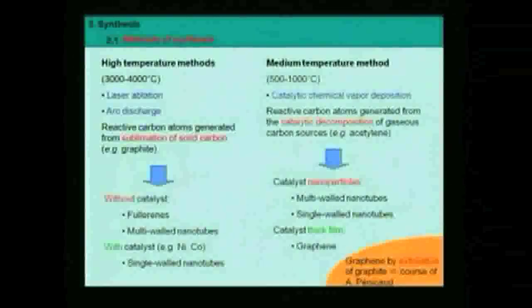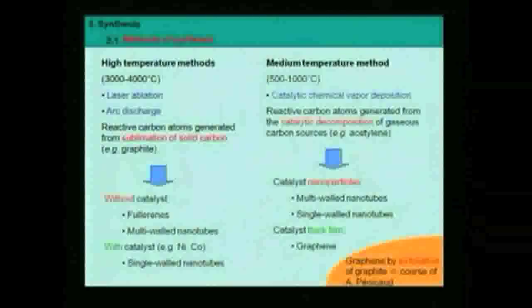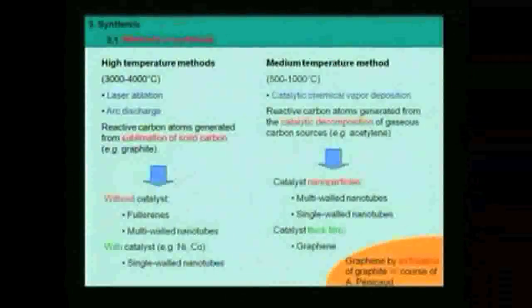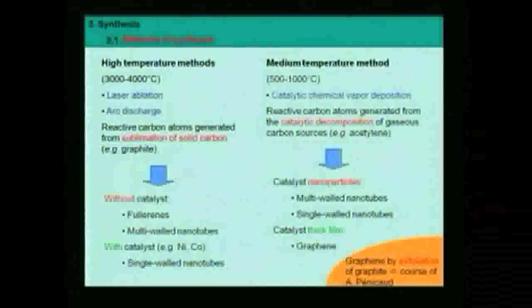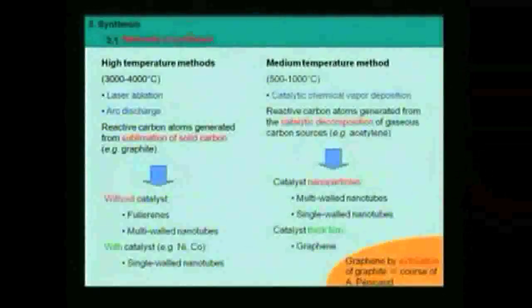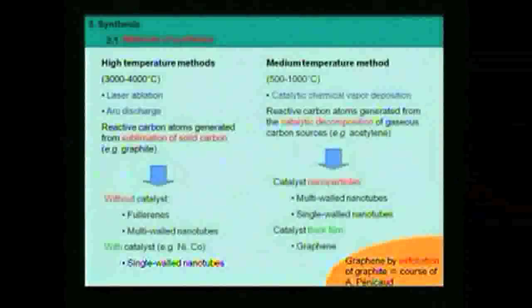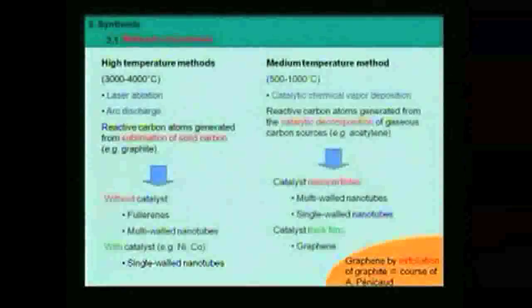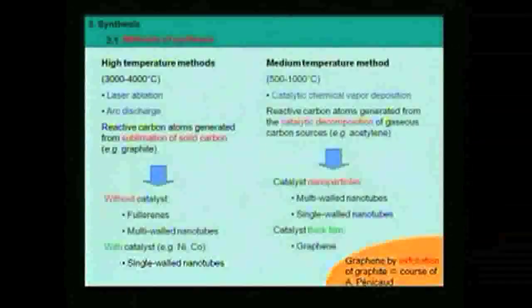If you use nanoparticles, you will be able, by a template effect, we are going to talk about that later in detail, to obtain nanotubes, either single-walled or multi-walled. If you use a thick layer of catalyst, then by this template effect, you will not grow a tube, but you will grow something flat, that is graphene. Graphene either with a single layer of graphene, or maybe, in some cases, several layers of graphene stacked together.